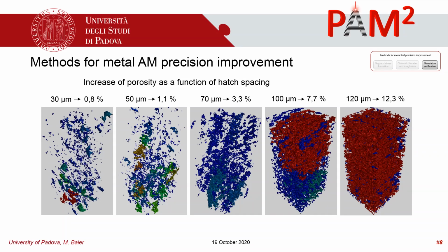As an example, the 5 images below show the porosity detected in the region of interest of the CT scans. By comparison of these values with the ones obtained by the simulation, it is possible to determine the goodness of the simulations and also to further improve their congruence with the real processes by readjusting the simulation conditions.